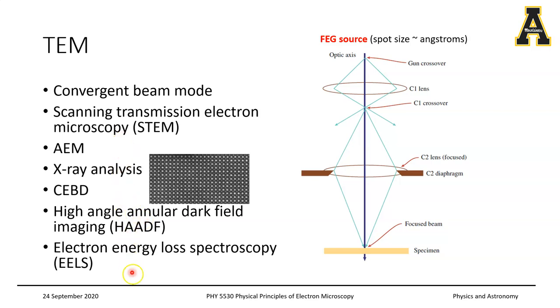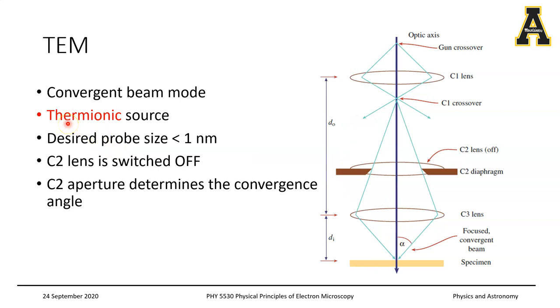If you were using a thermionic source and still wanted to do a convergent beam mode measurement, the optics would be slightly different. In that column you would have another lens, your C3, and the C2 lens is turned off, but there is a C2 diaphragm or aperture which is important in determining the convergence angle incident on the specimen. You still have your gun and C1 lens, a diaphragm that limits the solid angle, and then the C3 lens focuses everything into a tight spot — typically less than a nanometer — but in case of a thermionic source the demagnification has to be tremendous, which is why you have more lenses in the optical column.